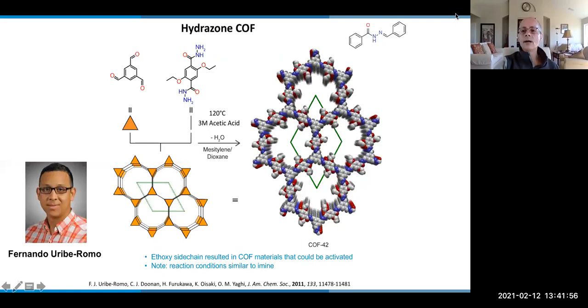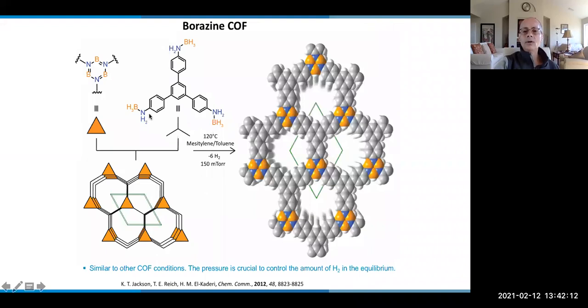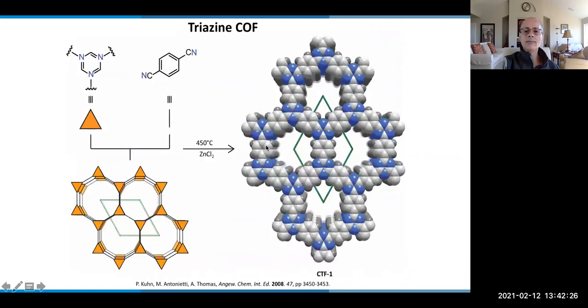Okay, beyond imines, we can go to hydrazones. I'm going to zip through these, but keep your eye on the conditions. We're using acetic acid, same conditions as the first COFs, to crystallize the hydrazone COFs. Also, my former student was successful in crystallizing these borazine ring linked COFs. This is a very nice report from Arne Thomas's group. They use very high temperature to crystallize these triazine-based COFs.